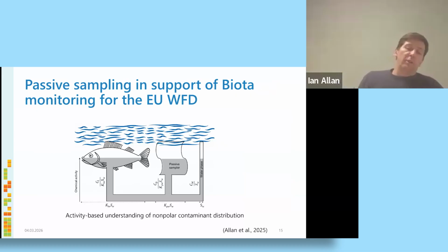In an ideal situation, where all the phases, whether it would be passive sampling or the fish, were at equilibrium, the activity in all the different compartments would actually be the same. This is a hypothetical situation because the fish is not likely to be at equilibrium. In the case of a fish sitting at a higher trophic level, biomagnification will tend to push that level up, and depending on how hydrophobic the chemicals are and how fast they accumulate in the passive sampler, they could be at equilibrium with the water, or they could still be very far from equilibrium. But that's the starting basis for the comparison that we've tried to make here.